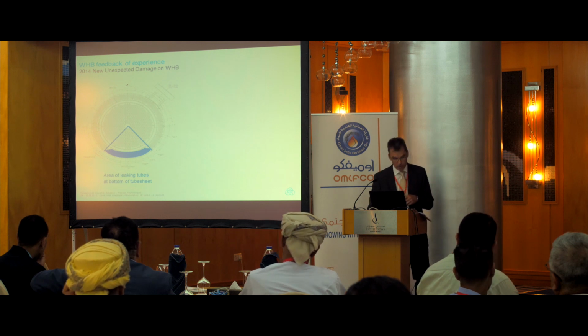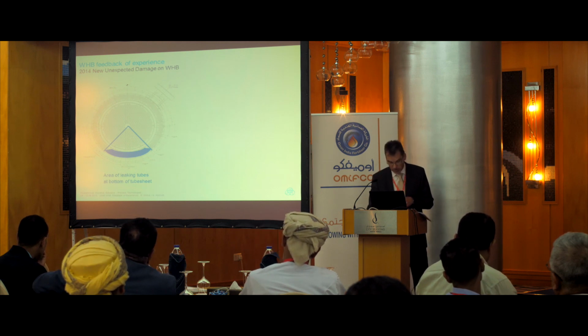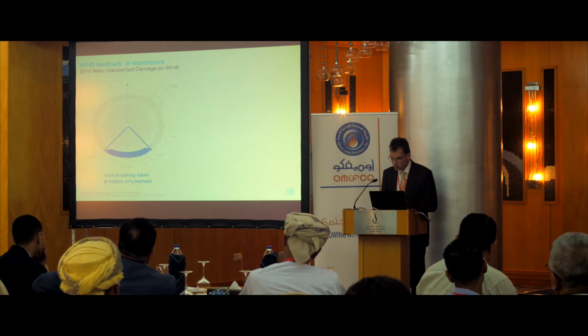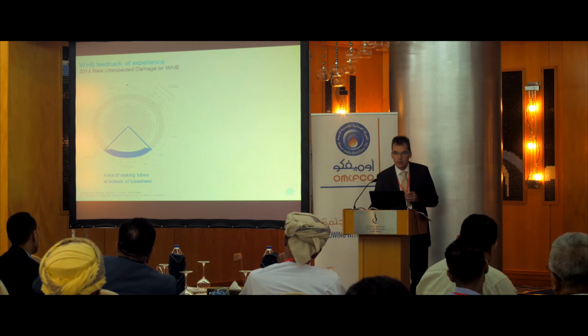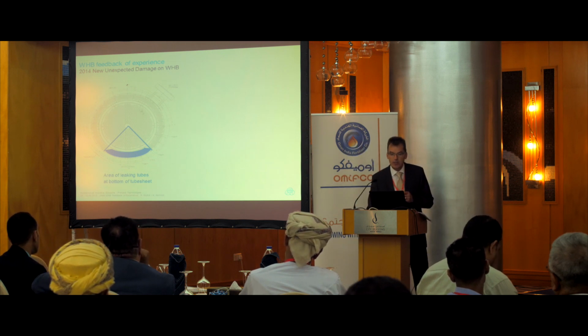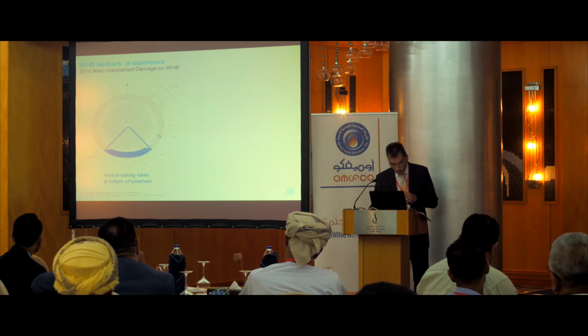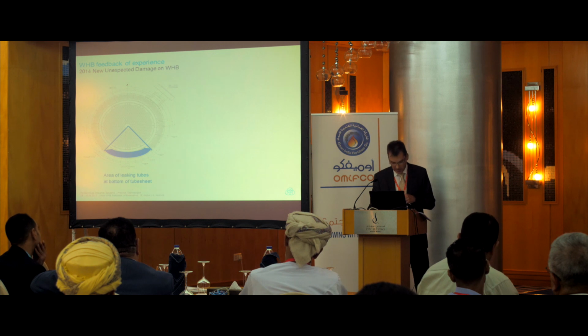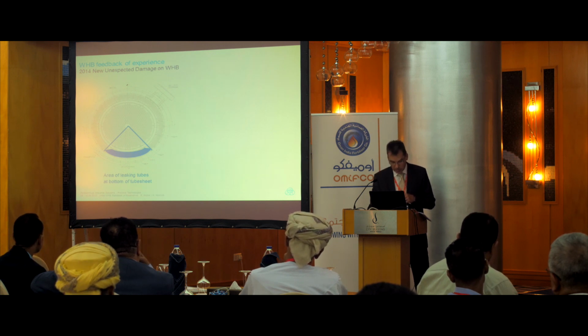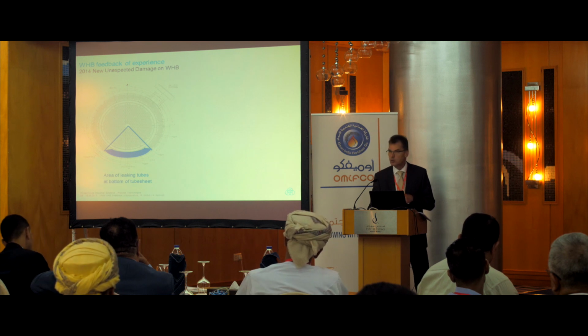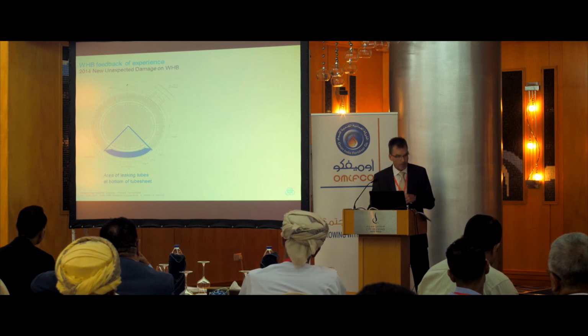Surprisingly, the leak in waste heat boiler 2 was not found in the hot inlet, but in the cold outlet tube passes. As you see here, the inner circle is the hot inlet, the outer ring is the cold outlet. Also, the leaks were not caused by tube wall thinning due to deposit corrosion. No, instead the leaks were a result of cracks within the tube-to-tube sheet welding seam. This was something new for us.